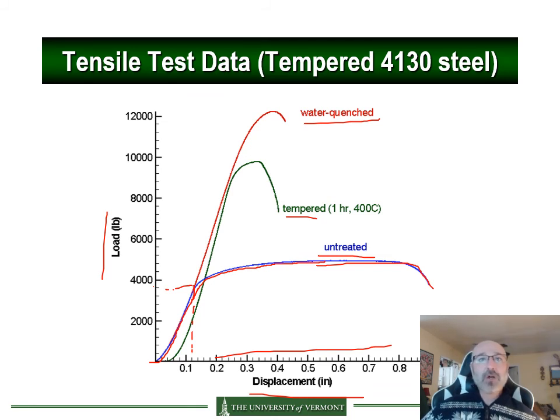Whereas if we have a water quenched one here in red, we can see this keeps going up. It pretty much follows that same curve at the beginning, but then it keeps going up when it's water quenched. We get a higher and higher load. Right here, we get up to over 12,000 pounds, and then it quickly falls off there. Whereas our tempered one here, we can see it does change the curve slightly, shifts it over to the right, a little bit more displacement, a little bit more elongation, and not quite as strong, just about 10,000 before it breaks off there. And this was tempered for an hour at 400 C.